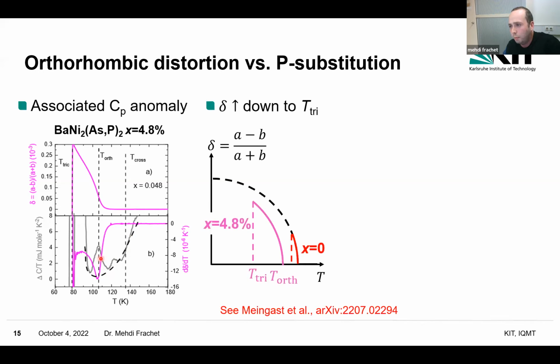Okay. So one point I would like to make is just to mention that it's actually not so easy to compare the amplitude of the orthorhombic distortion for different phosphorus substitution, and the reason for it is that you measure this distortion until you go into the triclinic phase, and so the temperature range that you have for this orthorhombic distortion to develop, especially in the undoped compound, is super small, like just a few Kelvin.